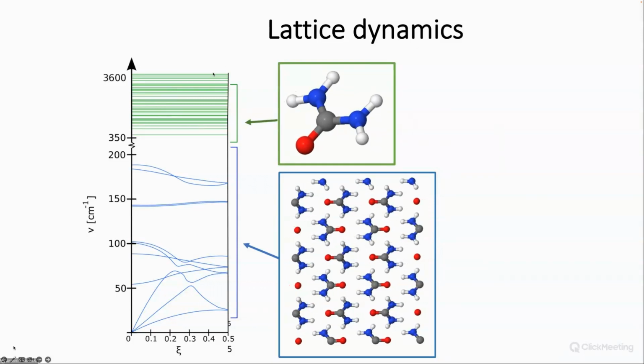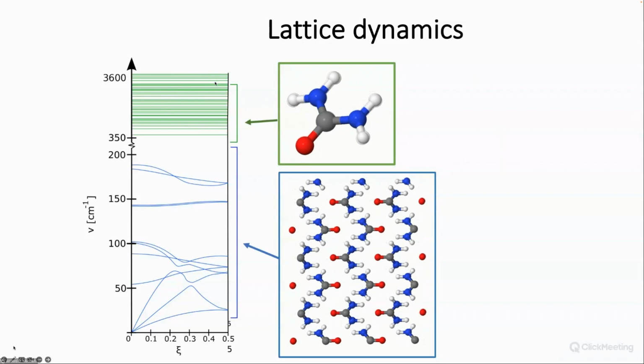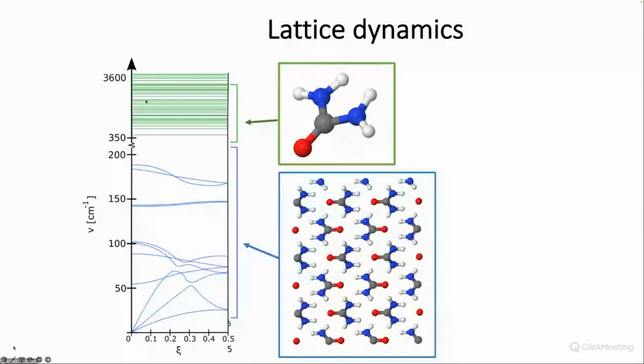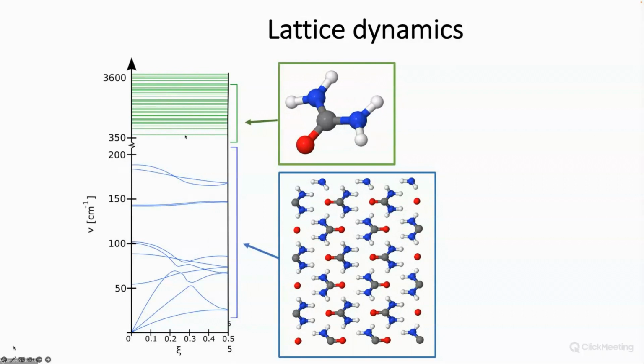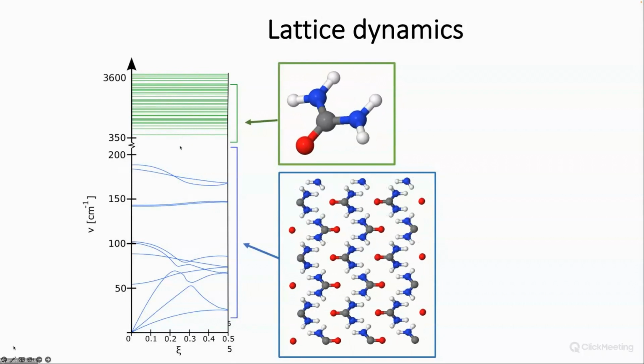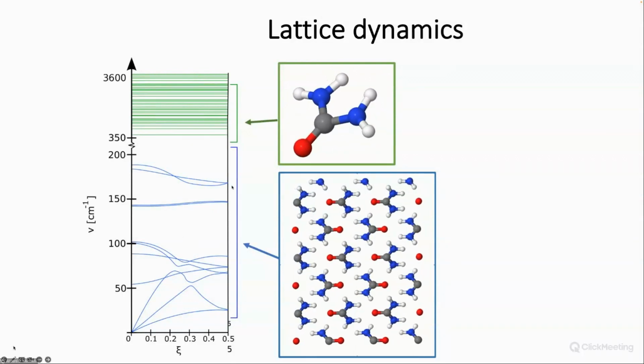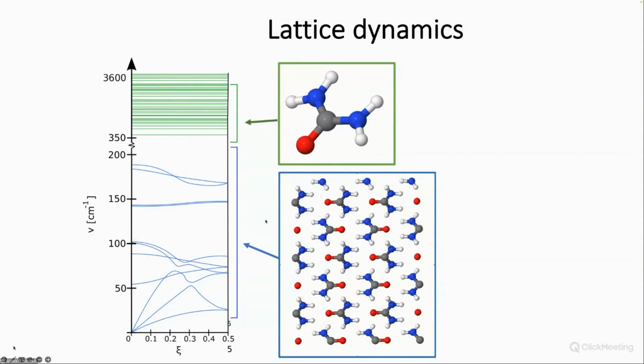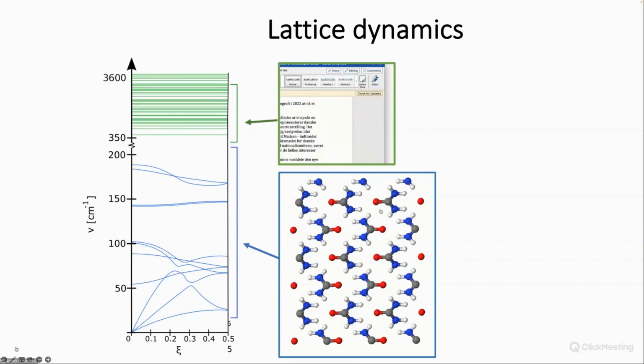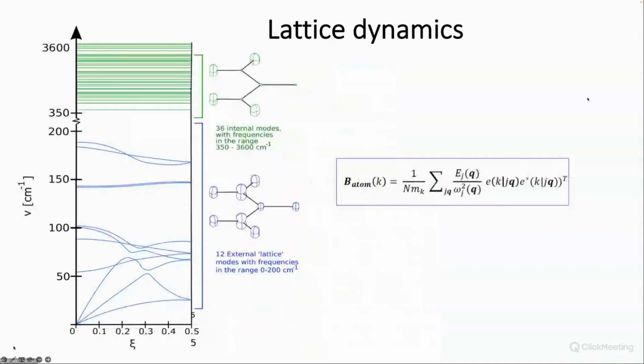You can see the high frequencies, which are up here, the green ones, are the internal modes of the molecules, whereas the low frequency modes are related to larger thermal displacements, giving rise to a larger contribution to the atomic displacement parameters that we derive or see from X-ray crystallography.